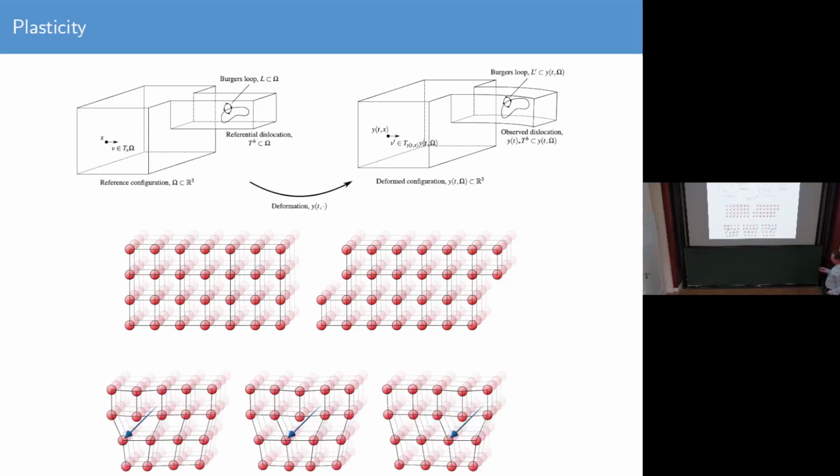So what really happens in real crystals is that they are not perfect. They have these defects. Here you have a line defect, which is called a dislocation. You see you have fewer lattice columns at the bottom than at the top. A more efficient way of moving here is by just cutting this row of bonds and flipping them over to that side. Then you see the dislocation has effectively moved one lattice spacing to the right. If you keep doing this, like some sort of caterpillar move, you end up having shifted the top bit of the crystal by roughly one lattice spacing.